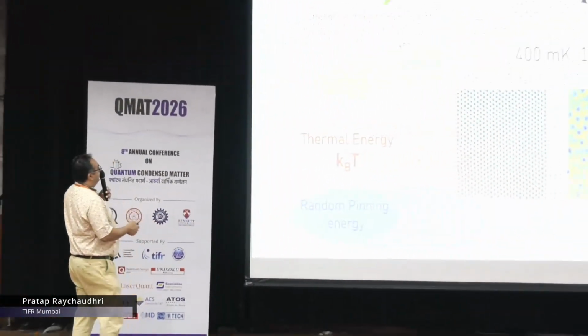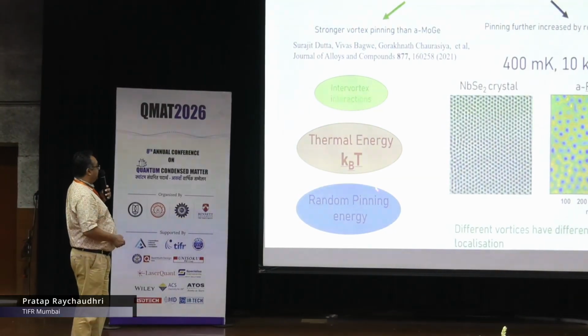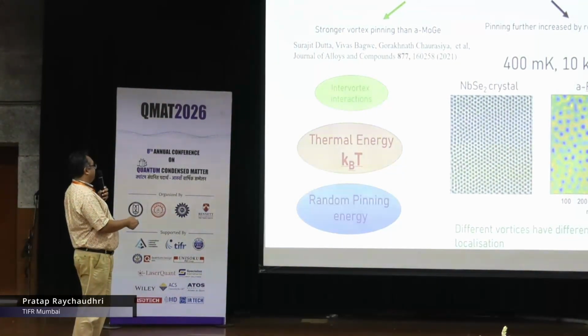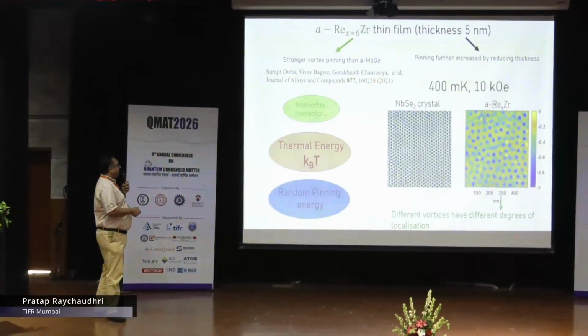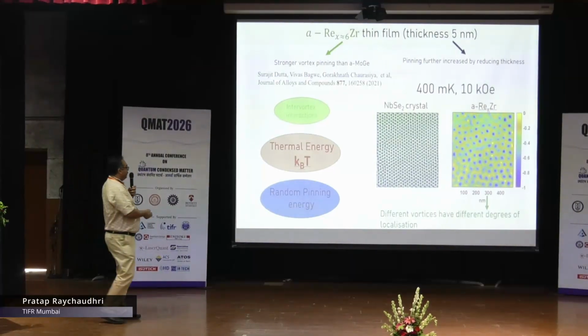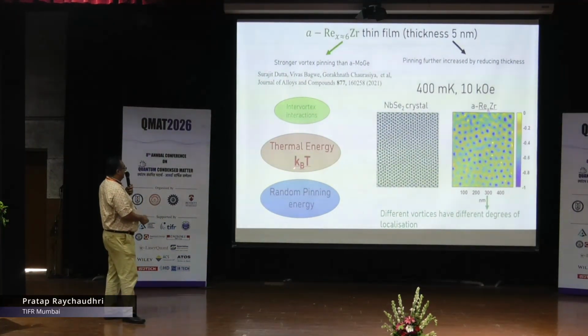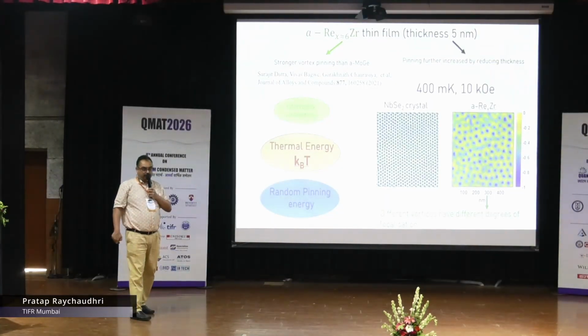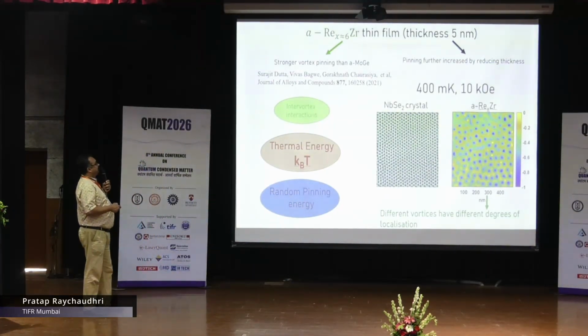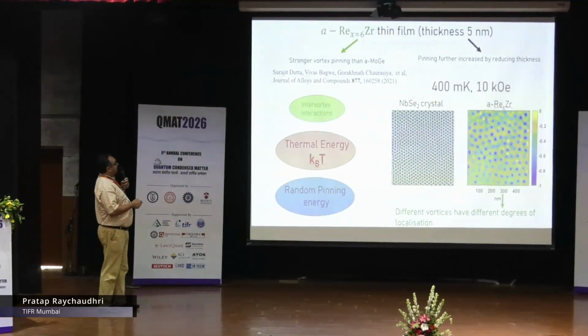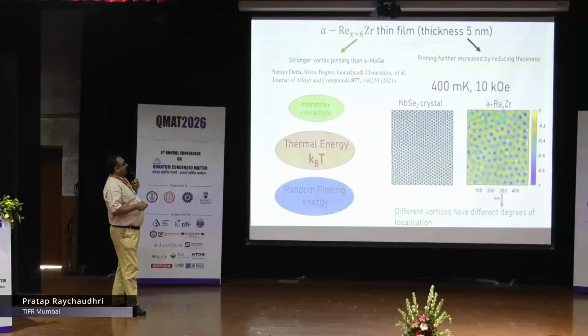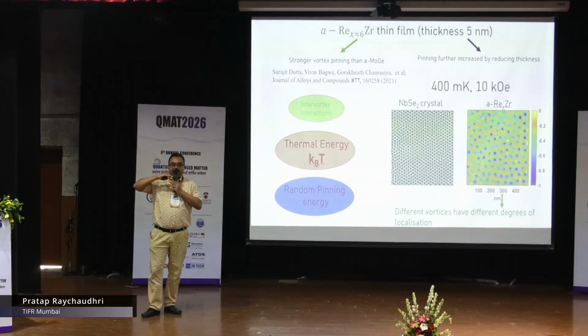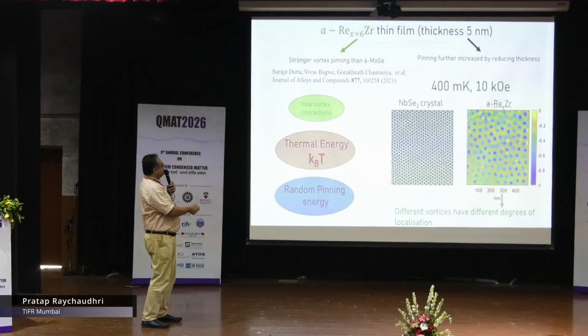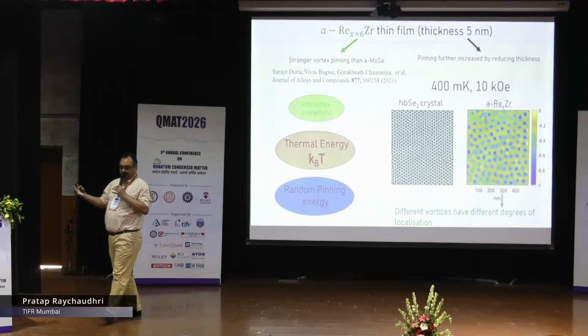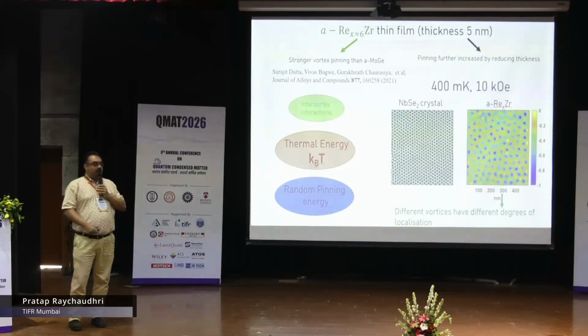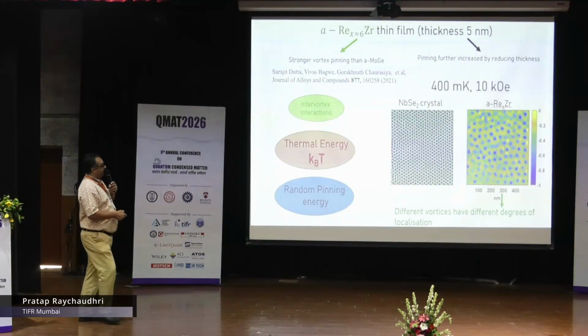Okay, so now I have shown you earlier where we had the thermal energy and the intervortex interaction competing. Let me go to the other end of the spectrum where intervortex interaction is not very important, and I have thermal energy and random pinning energy competing. For that I need to increase the random pinning strength, and we use another amorphous superconductor called rhenium zirconium. Here, since pinning mainly comes from surface defects, if I reduce the thickness of the sample, then the surface to volume ratio increases and effectively my pinning increases. So I decrease the thickness from 20 nanometer to 5 nanometer.